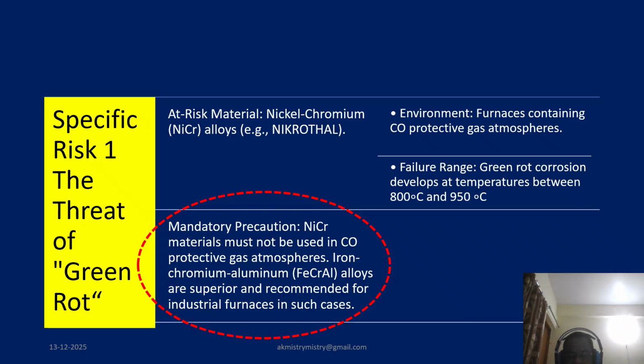The green rot threat is specific to nickel chromium alloys like Nikrothal. When used in furnaces containing a carbon monoxide protective gas atmosphere, this type of corrosion develops rapidly within the critical temperature window of 800 degrees centigrade to 950 degrees centigrade. Therefore, it is a mandatory precaution that nickel chromium material must not be used in carbon monoxide atmospheres. Iron, chromium, aluminum alloys are very superior and required in this industrial furnace scenario, and are best to use.